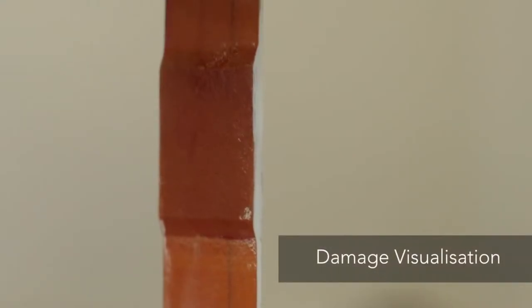The first is where we're trying to deploy healing upon the actuation of the damage event, so it's stimuli triggered. What we're looking at is how we can flood the resin system through the fracture plane in approximately 20-odd seconds.